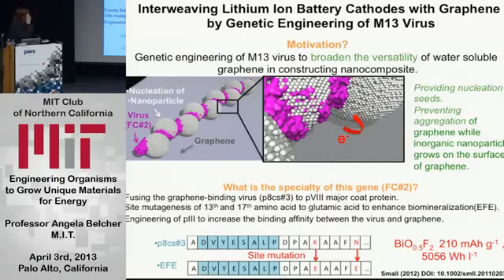So we actually moved on from carbon nanotubes and started thinking about graphene, because graphene was such a hot topic too for many different kinds of applications. And so we started genetically engineering our viruses to be able to bind to graphene and then grow other materials simultaneously. This material was bismuth oxyfluoride, which has a high gravimetric energy density, and we showed that we could get it to bind there, and that we could do additional selection and additional site-specific mutations to make it actually better.